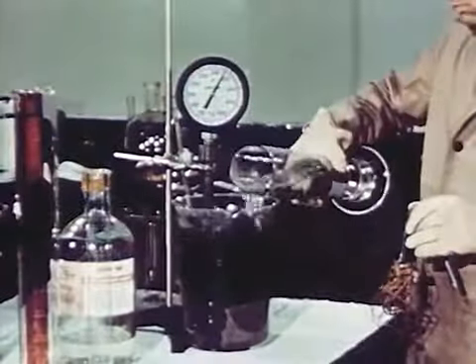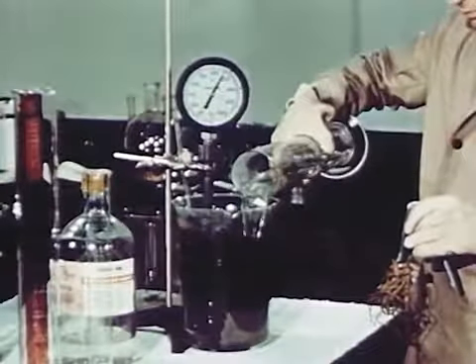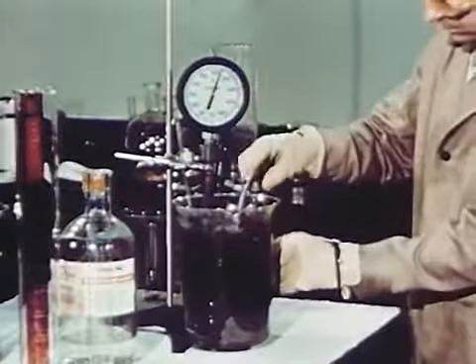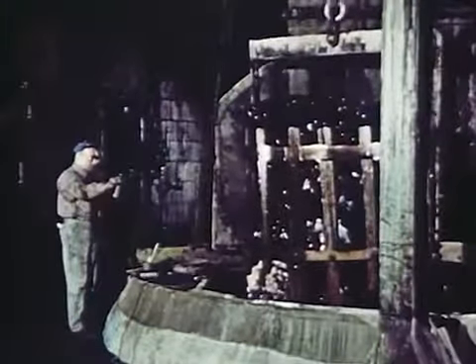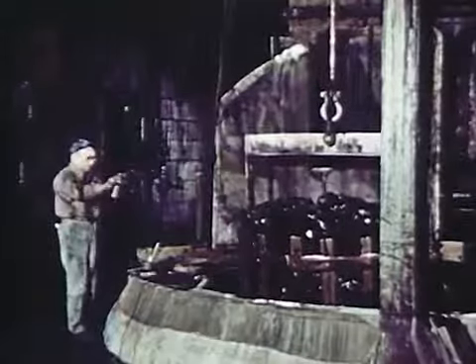When the reaction is complete, the mass is dissolved with water. At this time, a small amount of scrap iron is added to reduce chemically the iron in solution and so prevent it from oxidizing and becoming a source of contamination. In actual production, in a tank over 17,000 times the size of the laboratory glass beaker, it takes 15 hours for the maximum amount of ore to be dissolved. And this is only one tank in the battery of similar tanks that must be used and staggered for continuous volume production.